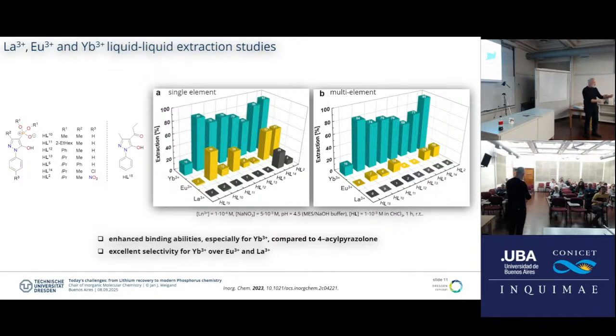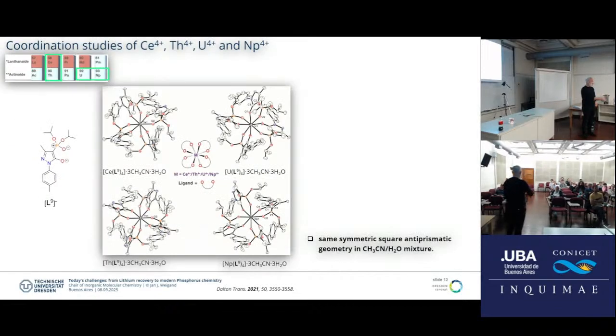By adjusting the electronic effects, by adjusting the sterics and so on, we really get selectivity, which is normally quite a problem. If you think about rare earth metal purification, you need a lot of mixer settlers, a technology typically used that is football fields long. Now if you are more selective, you can reduce the size, you're more sustainable, you need less solvent, and with a better extractant you have much better separation factors and purification in order to really have pure rare earth metals in the end. We did not only look into rare earth metals, we also looked into actinides, and that's something which we are able to do.